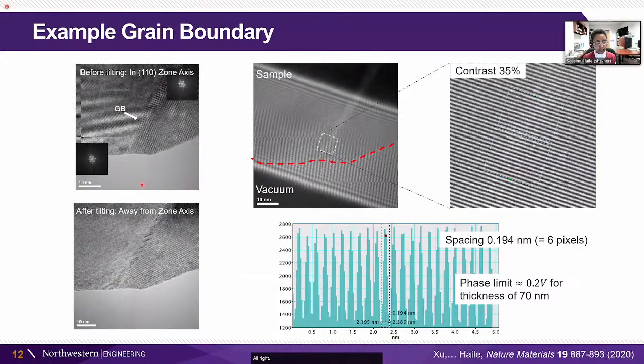All right, so here's an example where we've taken an FIB cross-section, so a focused ion beam slice out of our polycrystalline sample. Here's the grain boundary. We tilt it slightly away from the zone axis. Hard to see here, but this is the electron hologram. And right here is that grain boundary. We go in and zoom in. You can see the hologram has very good contrast, and that's what we're able to use to now reconstruct the phase information.